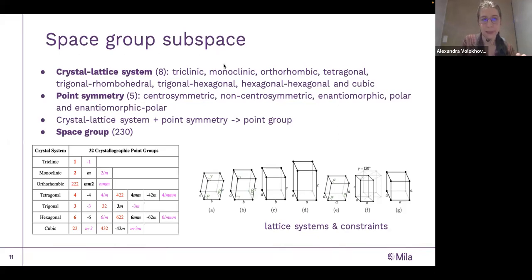And that's why we introduce all these additional parameters. In this space, Diffonet is allowed to sample these parameters in any order. It can start with the crystal lattice system, with point symmetry, or with the space group. And once one of them is sampled, it may introduce some constraints on the others. So if the space group is sampled, then the point symmetry and crystal lattice system are uniquely defined. But if the crystal lattice system is sampled, then we have some restrictions for the space group, but it is not uniquely defined. So we also make use of all these geometrical constraints.